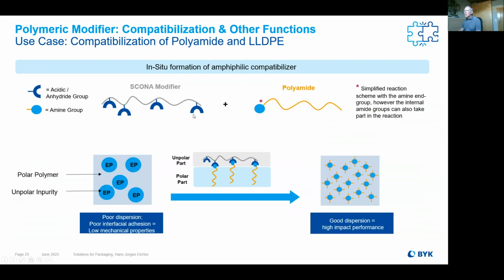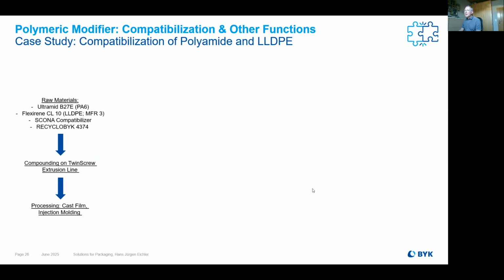So here is, of course, how it works. We have the SCONA modifier, and here these blue half pipes should give the functionality group. That means here we have a maleic anhydride group. And for example, if we have now a polyamide, which has on one end the amine group, it can react with the maleic anhydride. And what is going on then is you have a compatibilization between the different phases. So you have a nonpolar and a polar part, which are now really bonded and really nicely dispersed with high impact performance.